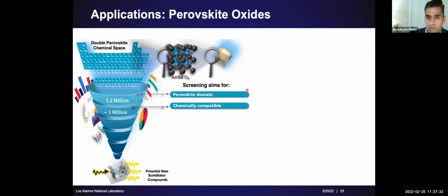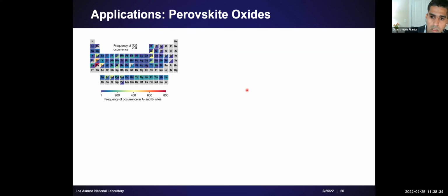We generate a data set of 3,500 compounds from first principles, using a consistent set of parameters that is compatible with the Materials Project data set, so we can calculate the thermodynamic stability in a global fashion in terms of energy above hull. By using whatever has already been calculated and known experimentally, and tabulated in the Materials Project database, we then use that data to build machine learning models that allow us to classify a new chemistry as a stable perovskite versus non-perovskite.